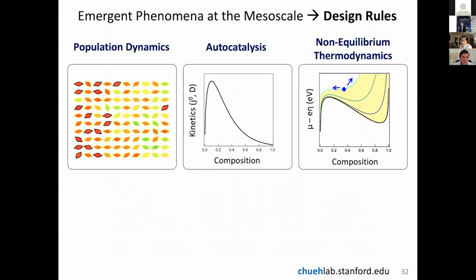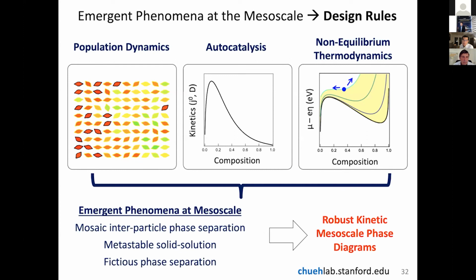So to wrap up here, I've covered three themes: population dynamics, autocatalysis, and non-equilibrium thermodynamics. I have taken what appears to be strange heterogeneity, but then we try to understand them at the mesoscale in informing the design rules. We have three emergent phenomena: the so-called mosaic effect of interparticle phase separation, or the population dynamics effect. I talked about metastable solid solutions, so going against thermodynamics when you have a current. And I also talked about the so-called fictitious phase separation, where autocatalysis amplifies heterogeneity in the system. And from this, we can derive a set of robust kinetics mesoscale phase diagram.